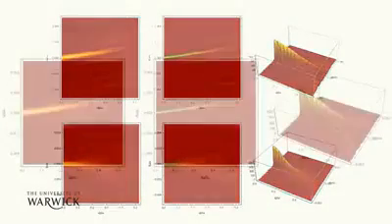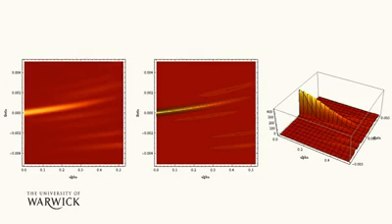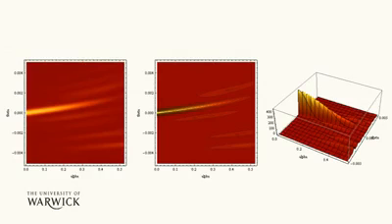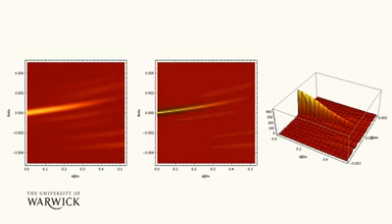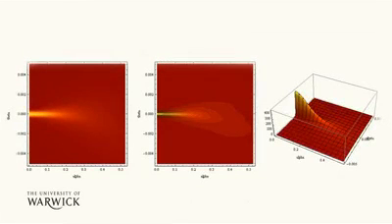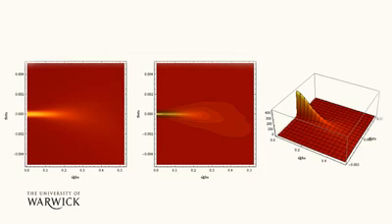What we see in the upper row is what would happen if we had a few short-range variations in the height. Besides the dominant main peak, you see side peaks appearing at other positions. The second row shows that when we average over many such distortions, the net effect is a broadening of the single peak. This broadening is faster than linear, as in the experiments, and hence different from long-range distortions.